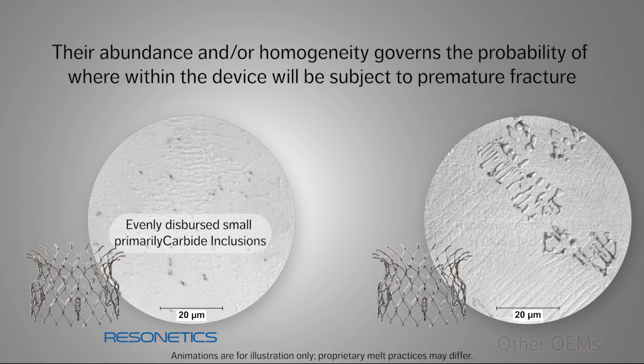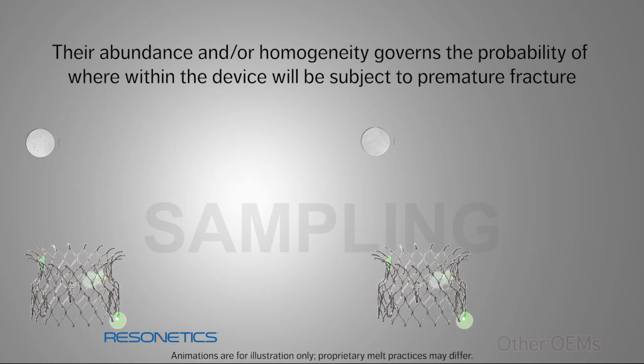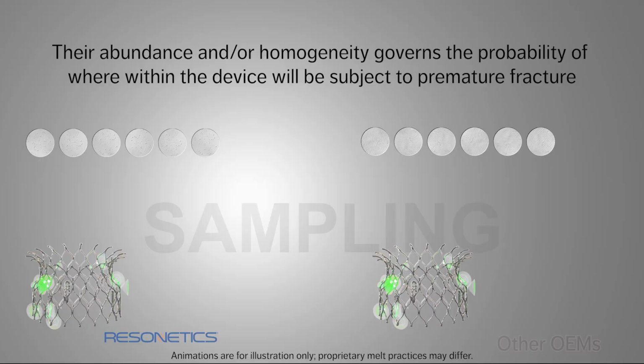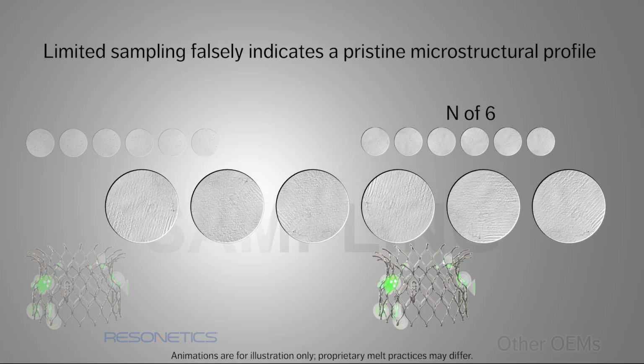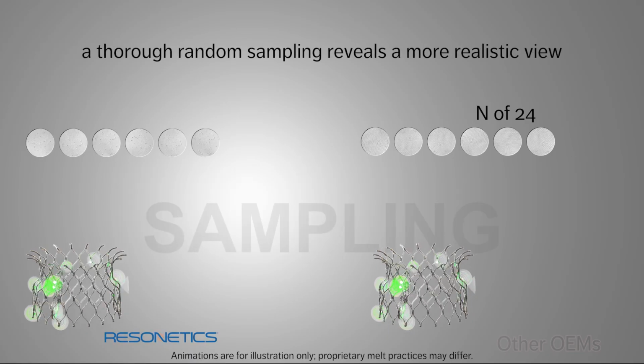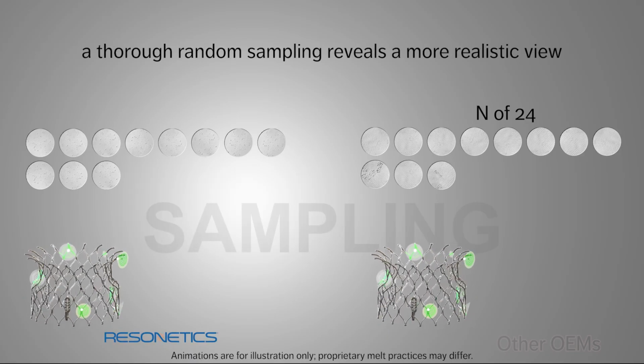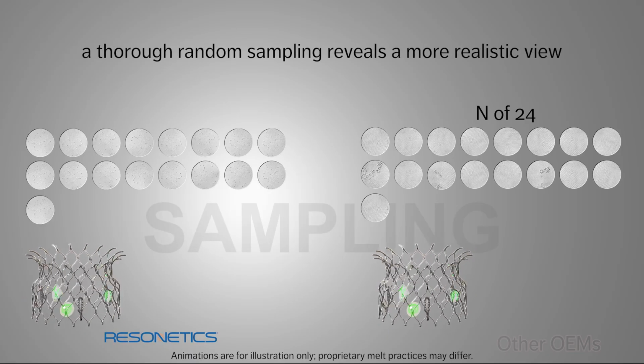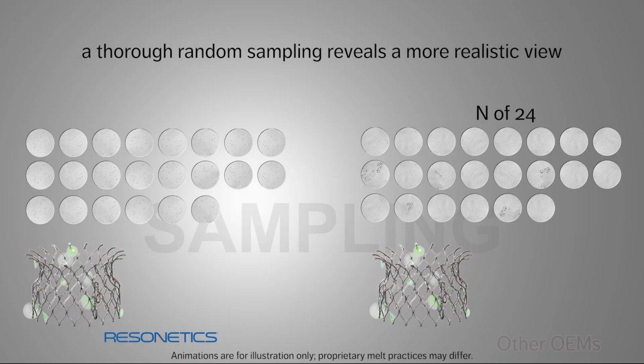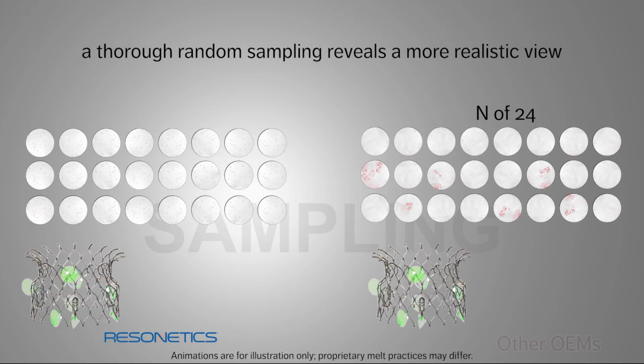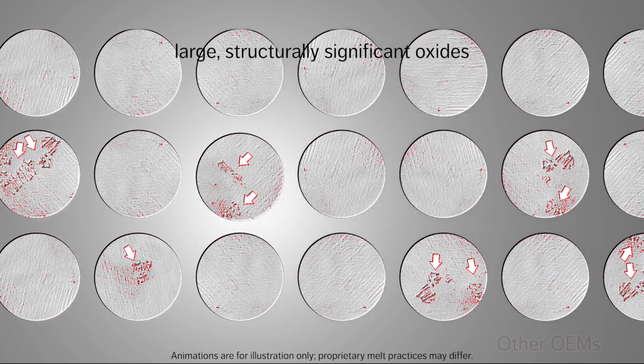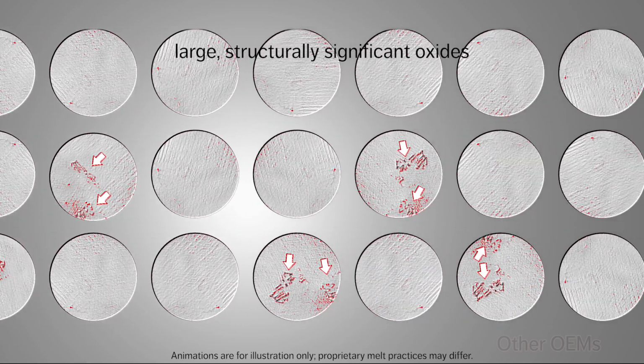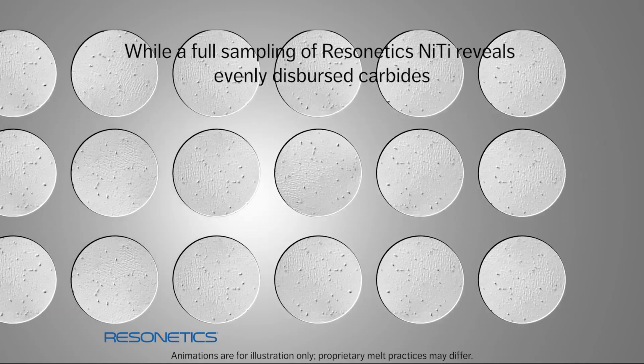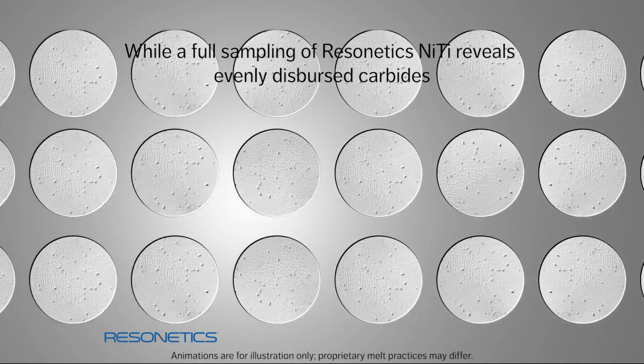The abundance and/or homogeneity of the inclusions governs the probability of where within the medical device will be subject to undesirable stress concentrations and therefore susceptible to premature fracture. Limited sampling can falsely indicate a pristine microstructural profile, but a thorough random sampling reveals a more realistic view. This closer look reveals large, structurally significant oxides, while in contrast, a full sampling of Resonetics nitinol reveals evenly dispersed carbides.